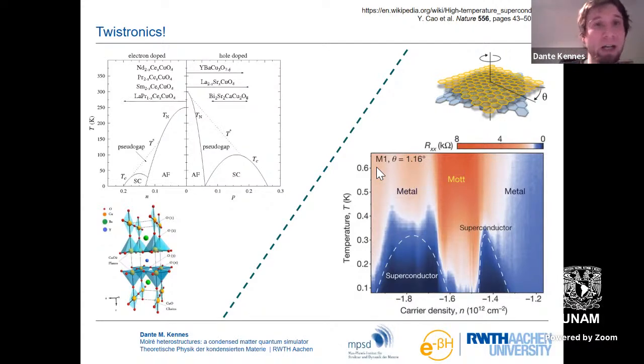Now that defines a very large Moiré periodicity. And the logic is to quench the kinetic energy scales by this large length scale that emerges, down to much smaller values, giving relative prominence to interaction effects. That's the driving theme. And now they measure transport, and what they see is there is an insulating state here for this particular filling of the system, and this insulator is flanked by superconducting domes. So when you look at this on a qualitative level, this somehow resembles the kind of structure that was reported earlier for these unconventional superconductors.